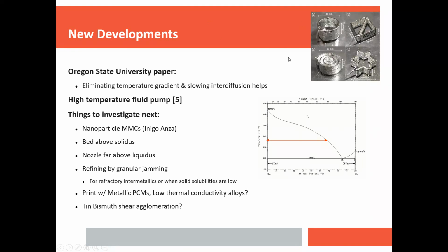At least on the time scales they were printing this, for sure. So that slowing of the interdiffusion plus the reduction of the temperature gradient really helps, especially if you can get the print bed to be around the melting point of the metal, or the solidus at least, or even above. So basically, their success there shows that there's a parameter space where this works. That's the fundamental thing there.